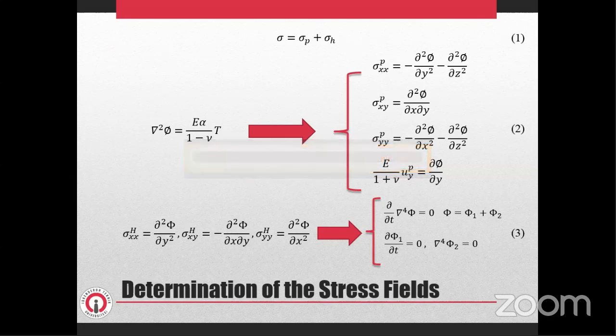We determined the temperature fields in the solidified shell, coating layer, and the mold in the previous slides. Thermoelastic stresses in the solid layers depend on the thermal and mechanical behavior of the system. Obtaining stress fields in the solidified shell, coating layer, and mold necessitates complex calculations, since the material is continually being solidified while the solid is in a deformed state. On the other hand, residual stress occurs in the final cast product even after the temperature of the casting has been reduced to the steady state value.